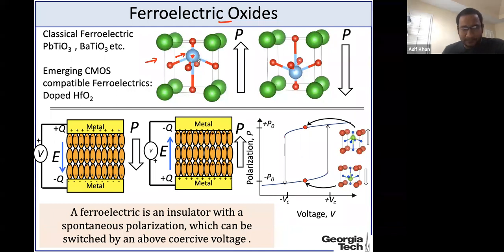structure. And that would mean that since it's off-centered, at the unit cell level, this material will have a dipole moment. And the most important thing is that this atom can be in this position or off-centered from the center of symmetry by the same amount on the other side. So in these two cases, this unit cell will have an electric dipole moment in two opposite directions. And the other important thing is that by applying an electric field, you can switch the direction of the dipole